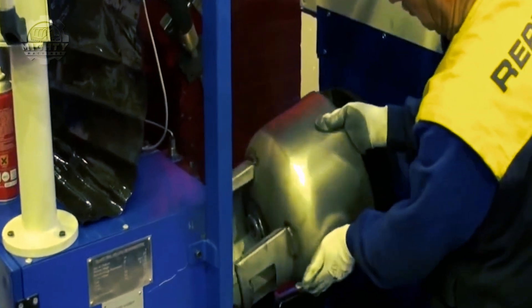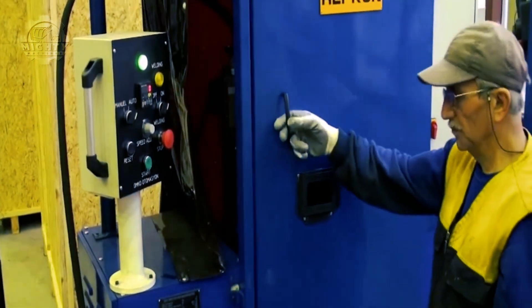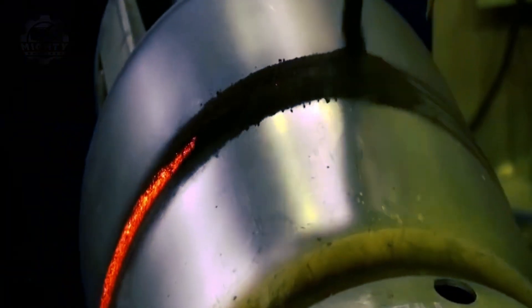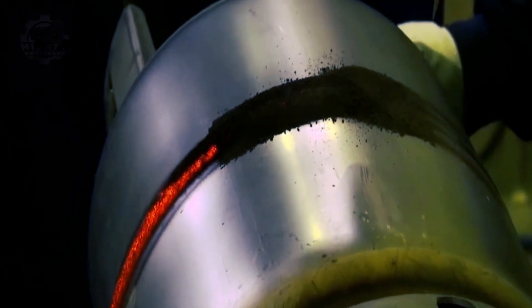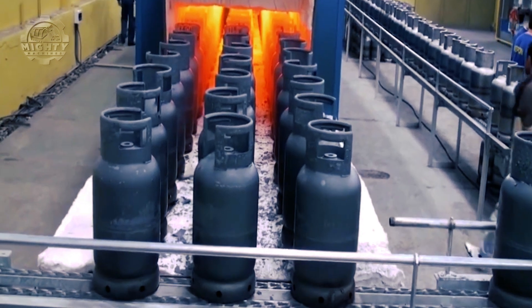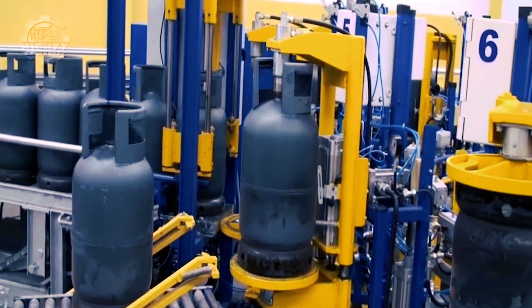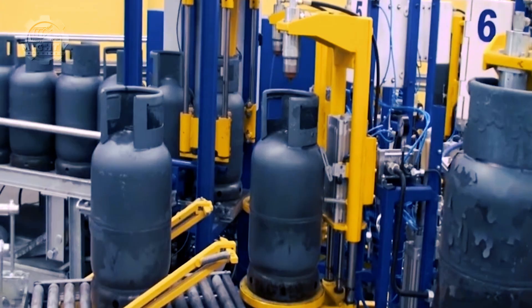Foot rings and valve guard rings are welded using the MIG-MAG process. Before cooling, cylinders are placed in a heat treatment furnace set at 930 degrees Celsius. Shot blasting is done on surfaces before painting or zinc spraying, and pneumatic leak testing equipment is used to check for leaks after the vessels are linked using torque-controlled screwing machines.